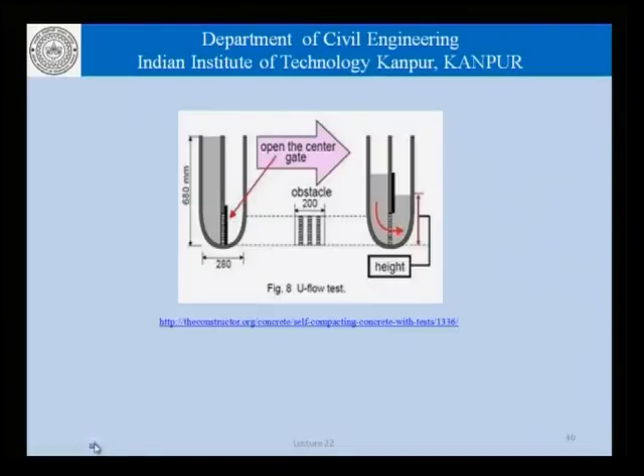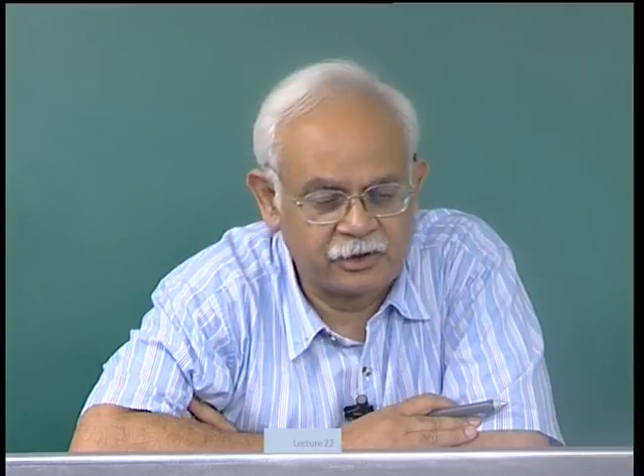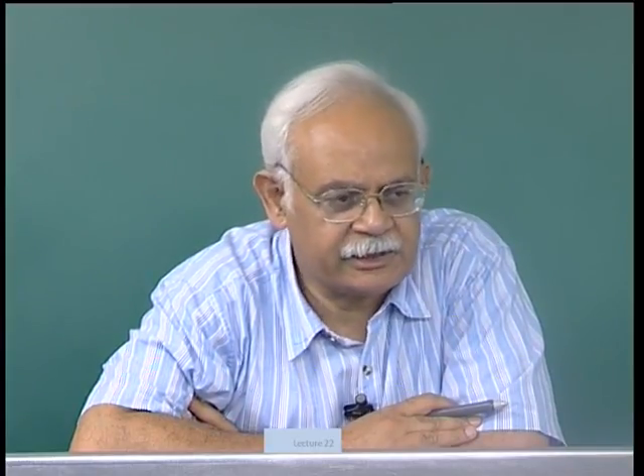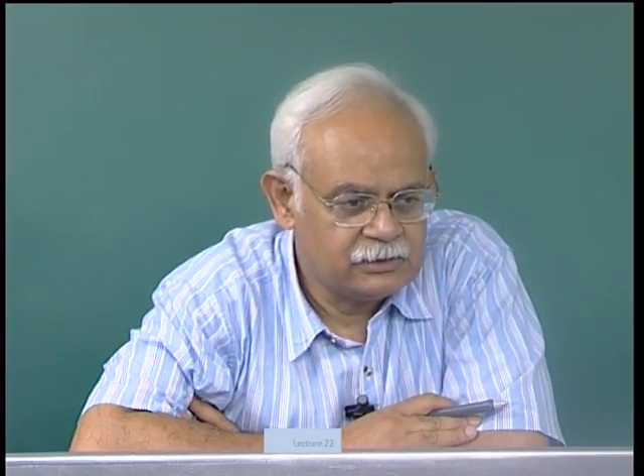Continuing with the tests, let us look at the U box test. As the name suggests, it talks about the flow of concrete in a U shaped box. So, concrete is filled on one end of a U box, closed initially with a gate, and this gate has an obstacle which again has simulated reinforcing bars. And once the gate is opened, the concrete flows from one end to the other, and we can always talk in terms of this height or the difference in these two heights. And again, if the concrete was a fluid or a liquid in that sense, then we do not expect any difference in the heights in the two sides of the U.